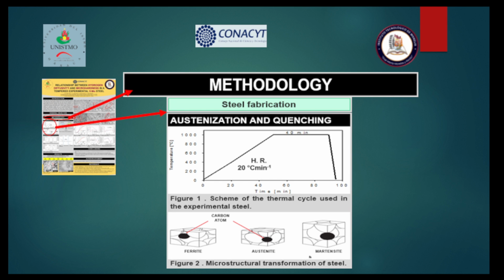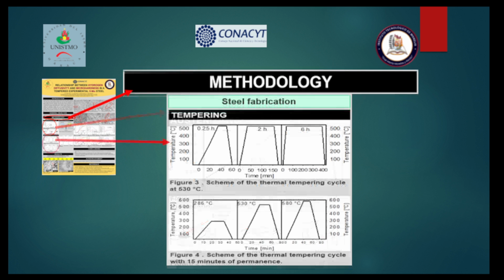The annealed steel was austenitized at a temperature of 1000 Celsius for 40 minutes and quenched in oil with stearin to obtain a martensitic microstructure. Subsequently, the tempering was carried out at two different temperatures, 530 and 580 Celsius, with 15 minutes of elapsed time. In addition, the tempering temperature of 286 Celsius was tested with 15 minutes of elapsed time to compare the behavior of the two tempering states.